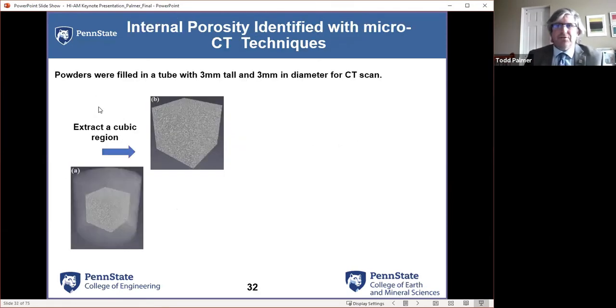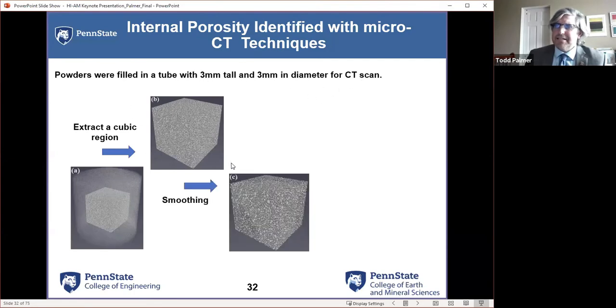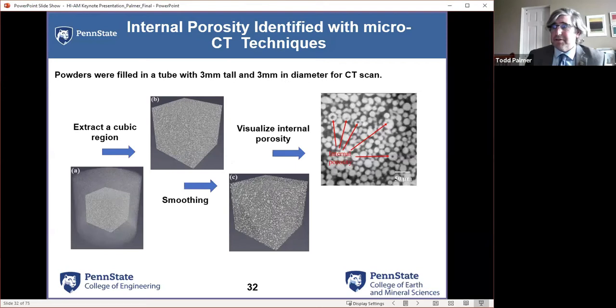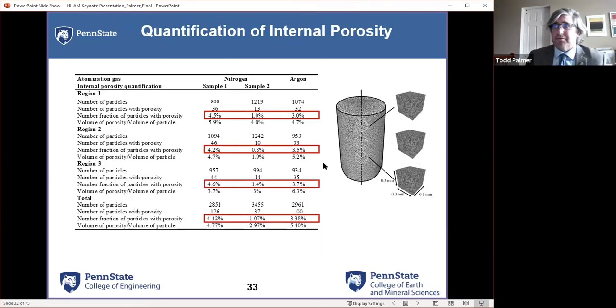So we wanted to try to get an idea of how much porosity is in powders, because you hear people talk a lot about, well, there's porosity in powders. There are some people claiming that the porosity is carried over to porosity in powder bed fusion or additive manufacture type things. And we're not going to talk about that right now. But we took some powders, we filled some 3mm by 3mm tubes, and we CT scanned them. Now, CT scanning is really cool. It's a way to look at differences in those. But if we start pulling individual scans out of there, we start seeing that there's a lot more porosity in these powders than we ever really would have thought.